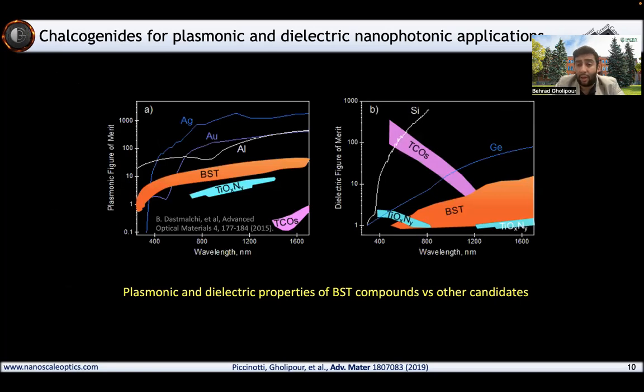Just to put things in context, look at what this can bring you, just as a measure of what is possible here. If we plot this material system that we just looked at, bismuth antimony telluride, BST, and we look at a plasmonic figure of merit and a dielectric figure of merit. Plasmonic figure of merit just indicates how many plasmonic wavelengths a plasmon can propagate before absorption basically reduces the energy, and absorption really kills that plasmon as it's propagating. The dielectric figure of merit is a slightly different case, where again, as I said, n over 4 pi k, we're looking at holding a particular wave within the dielectric medium and not dissipating the energy as much as possible.